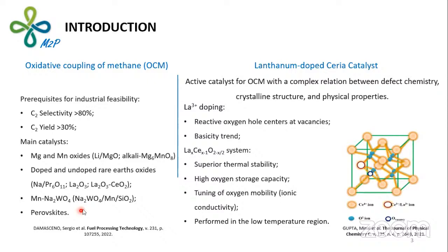Moreover, doped and undoped rare earth oxides, sodium tungstate doped with manganese, and perovskites have been reported as catalysts for OCM. The system where ceria is doped with lanthanum has shown good activity for OCM, with a complex relation between defect chemistry, crystalline structure, and physical properties. The doping with lanthanum produces reactive oxygen hole centers at the vacancies, and lanthanum has a basicity trend that makes this material suitable for OCM reactions. The system where cerium is doped with lanthanum has a superior thermal stability compared to the pure oxides. It has a high oxygen storage capacity, and this system allows the tuning of oxygen mobility, which is related to the ionic conductivity. And this reaction can be performed in the low temperature region.